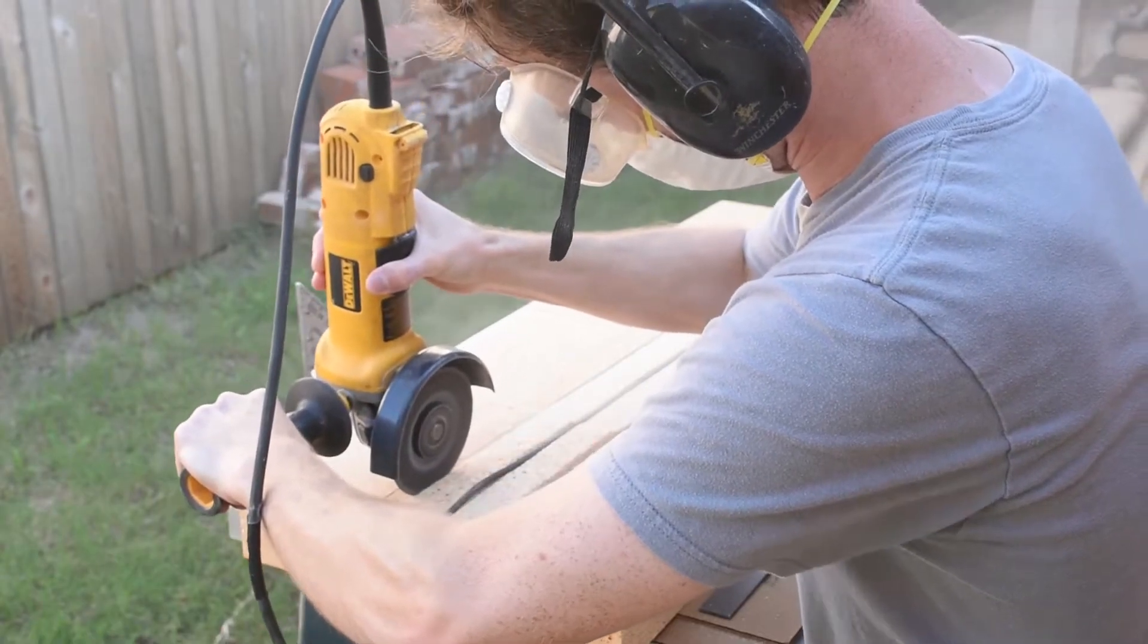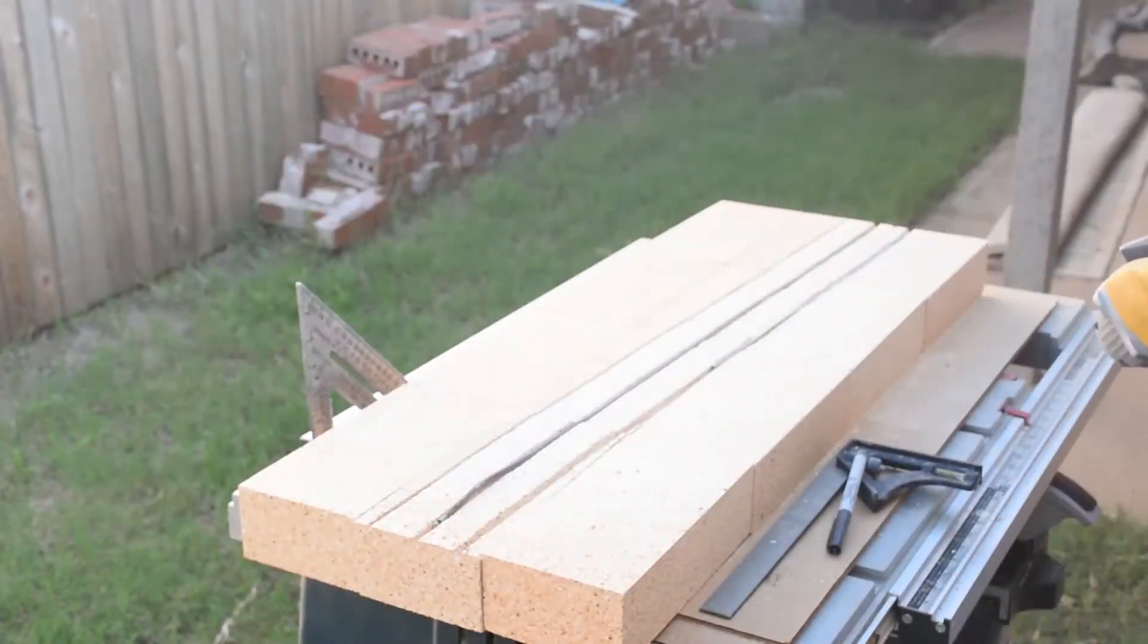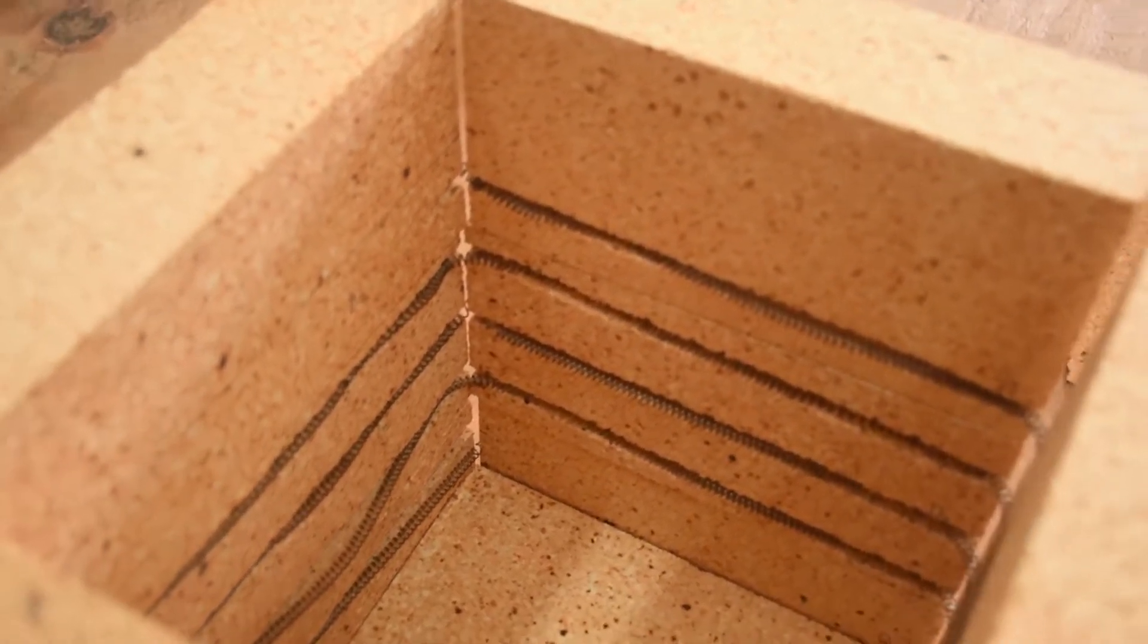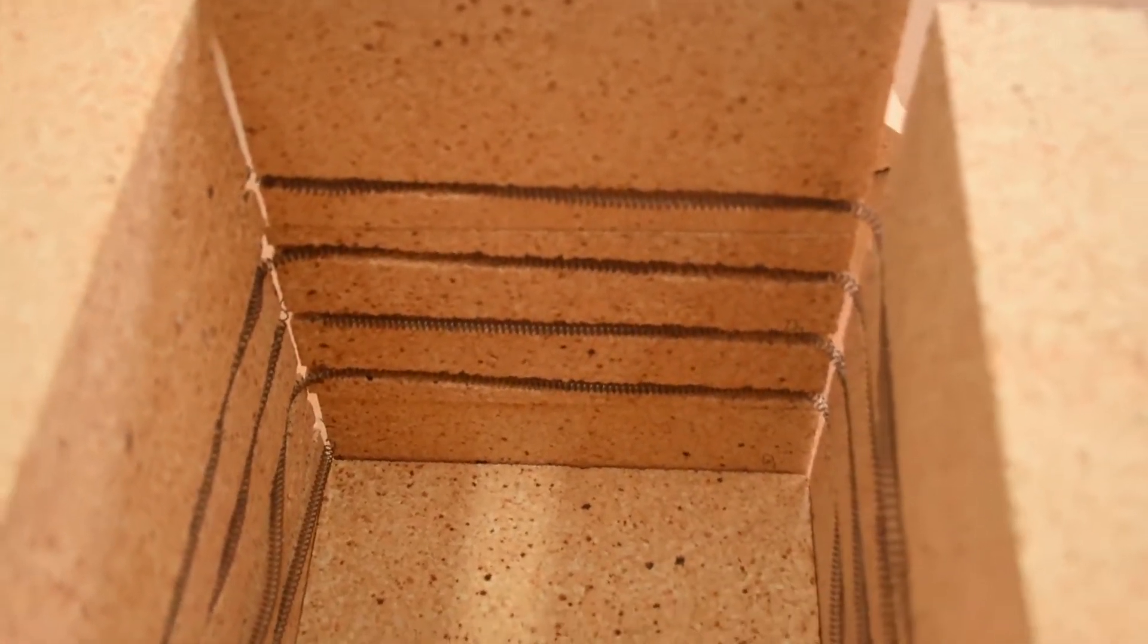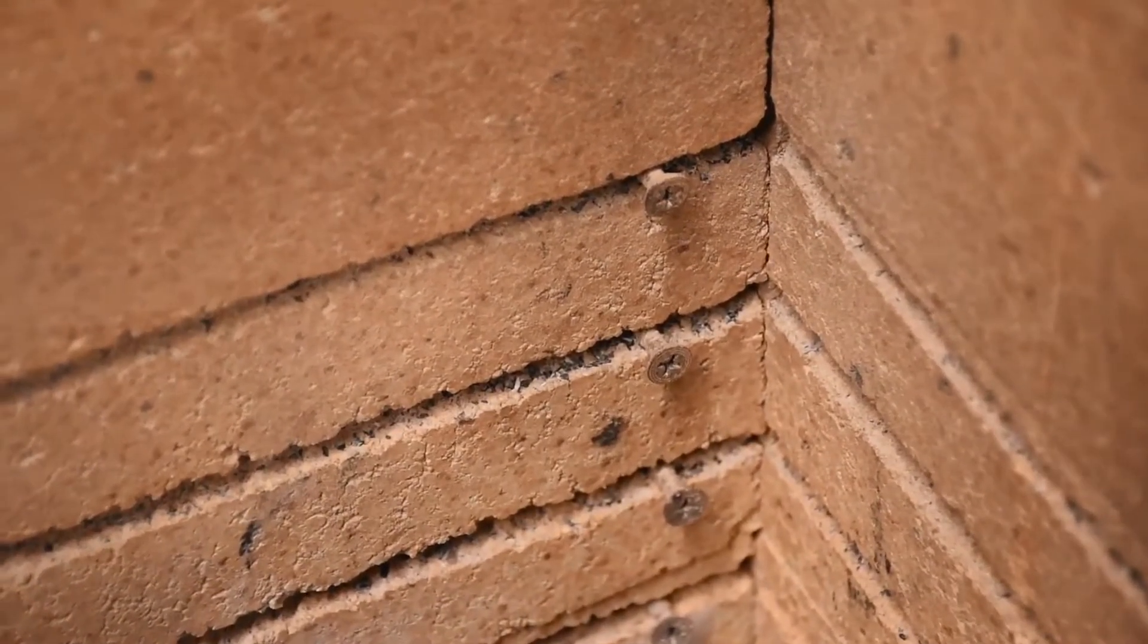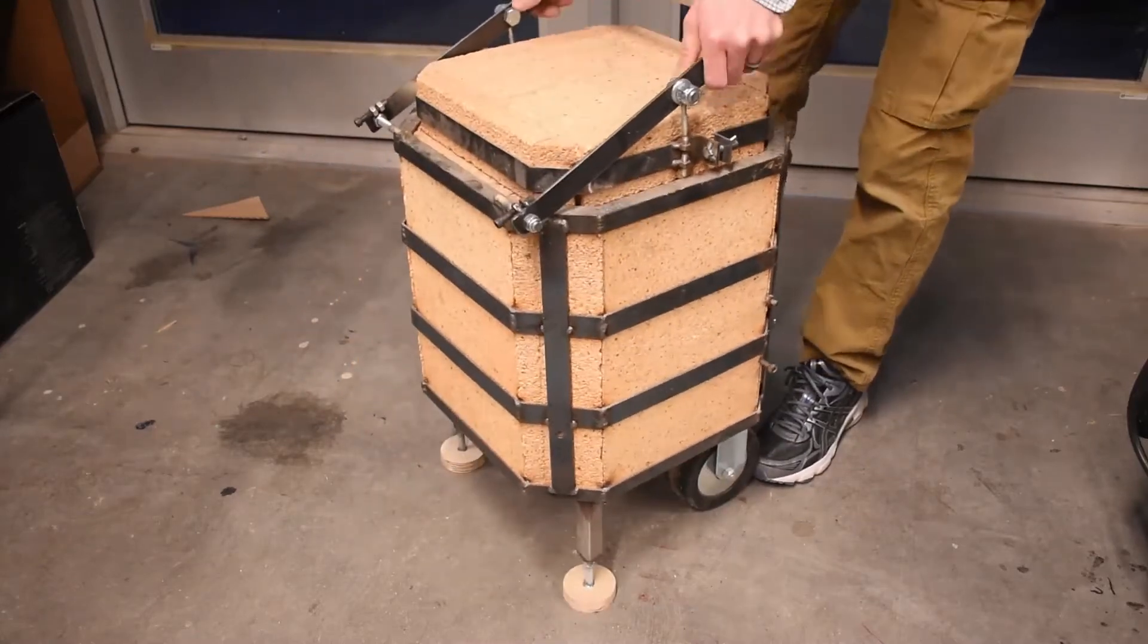My first foundry used two coils in a horizontal helix inside the walls and the coils tended to fall out of the slots once they heated and expanded. They shorted out several times when they touched and I had to replace three coils. It was a mess. I even tried screwing them into place and that worked somewhat but they still jostled around when I moved the foundry and eventually shorted out.